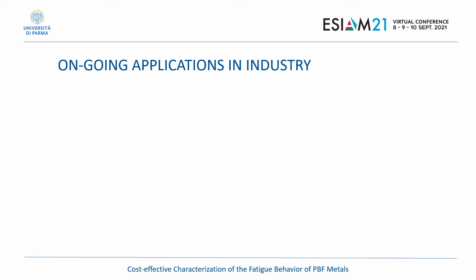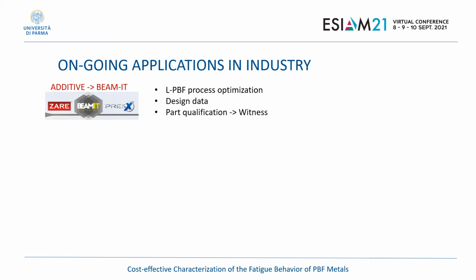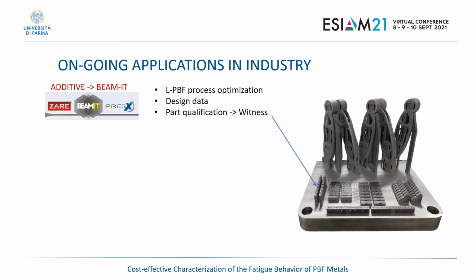The test methodology that we have been developing is now applied in industry. We have a number of cooperations ongoing. With BEAM-IT, we are investigating the problem of process optimization and fatigue data generation. In addition, we are investigating the possibility of using the miniature specimens as witness specimens, as you see in this picture, where we see the specimens along with the actual parts, so we can test miniature specimens produced simultaneously with the part that is to be qualified.